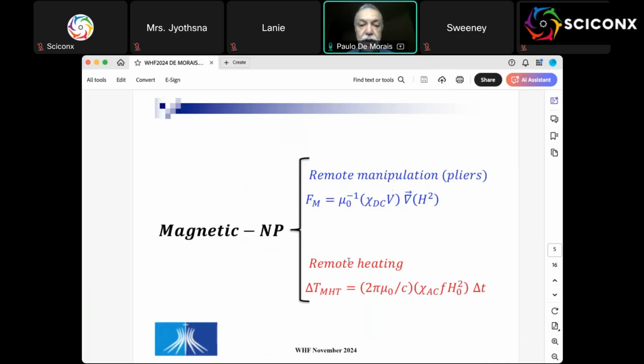And the heating is promoted by the amplitude of the applied external field, the frequency, and the AC susceptibility. So the heating, how much the temperature is increased due to the magnetic hyperthermia, scales with all these parameters. So the time, delta t, is the time that the AC field is applied. Here we have the amplitude of the applied external field squared, the frequency, the AC susceptibility, and the inverse of the specific heat of the medium. So these two relationships give you an idea how to control and how to manipulate the magnetic nanoparticles and place them at the right site where you want the magnetic hyperthermia effect to take place.